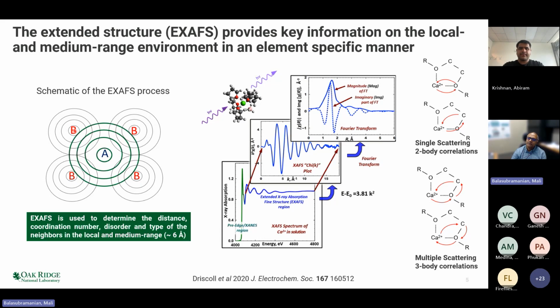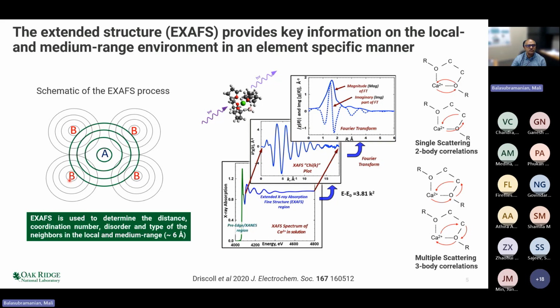The identity of the atom that is present here decides how much of these electrons would be backscattered and how much of its phase will get changed. So encoded in this EXAFS is an ability to determine the distance between the absorber and the backscatterer, the number of neighbors around it, which is often called the coordination number, and what is the disorder, that is, what is the relative disorder between the absorber and the backscatterer. And this process is essentially taking a nano image in a spherically averaged way for polycrystalline samples or for liquid electrolyte systems such as this.